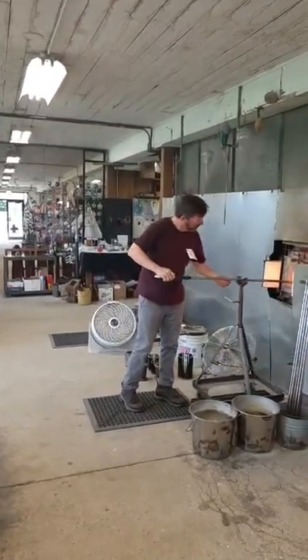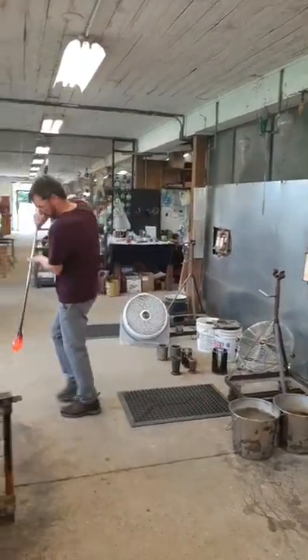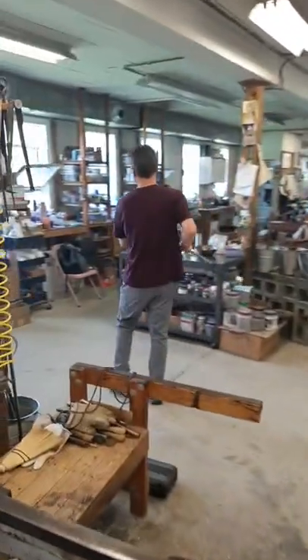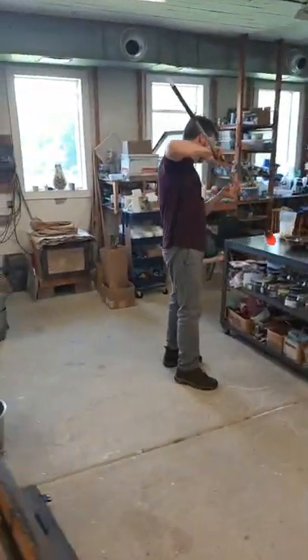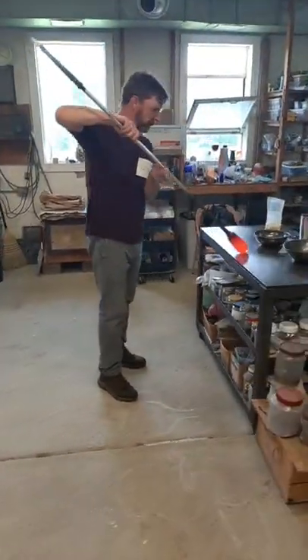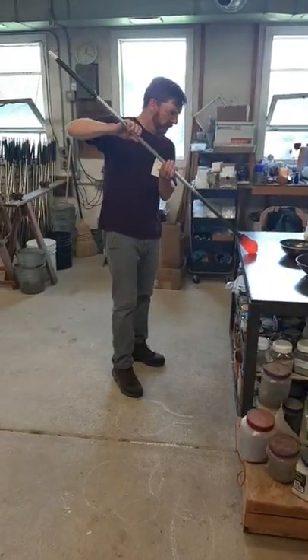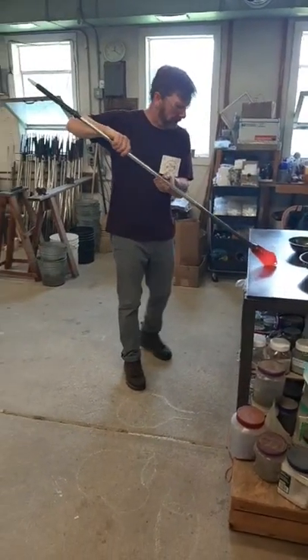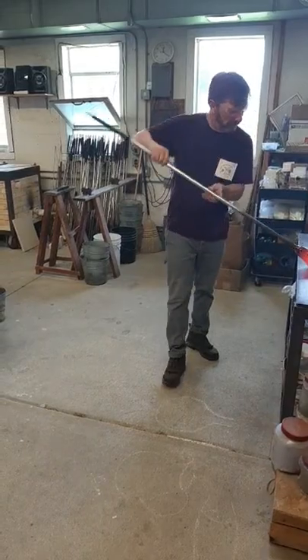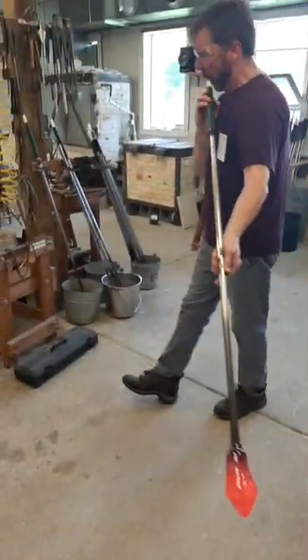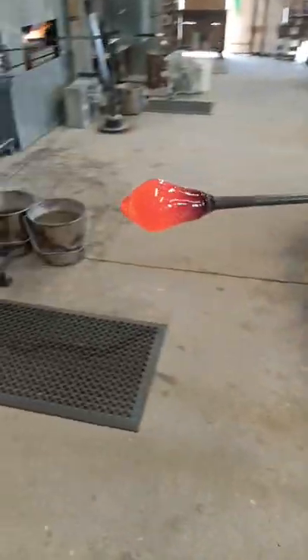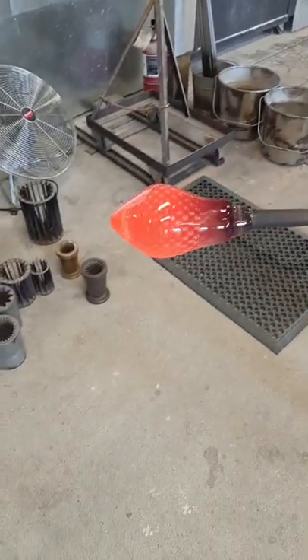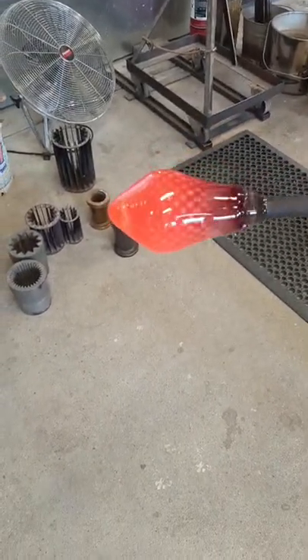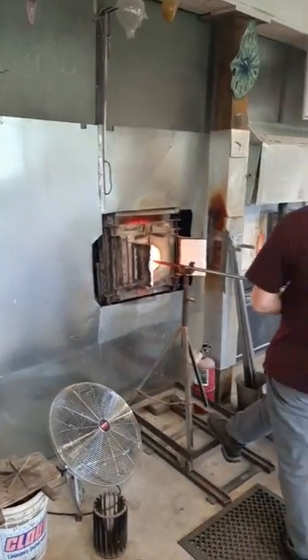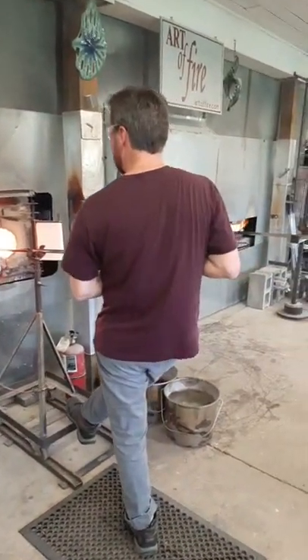So he waited a little while before gathering between those two layers. He's equalizing the heat, so he's got a little bit of work to do here. Notice when he inclines the iron downward, he cools that tip of the glass. That will not blow out, or not too much, and he traps the air bubble in there, and you see the expansion right up at the top, and you can see the bubbles appearing where the diamonds were.